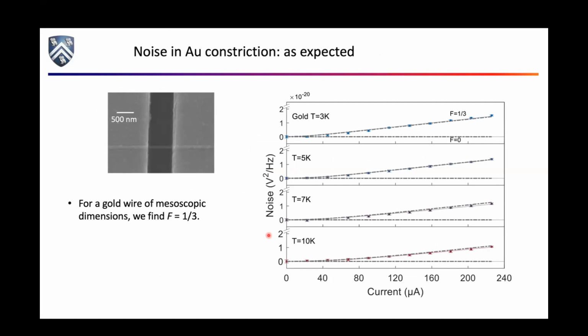Okay, so what do you see? Here's an example of a little gold wire. It's rather narrow, about 600, 700 nanometers long, with big, thick gold pads on either side. We made this thing at the clean room over here. And here we are at several different temperatures. The data points are in color with little error bars, and the error bars are the standard deviation, so this tells you how much scatter there is when you measure repeatedly. And what you see is that the gray lines are for the Fano factor equals 1/3, and it threads the data very, very nicely.